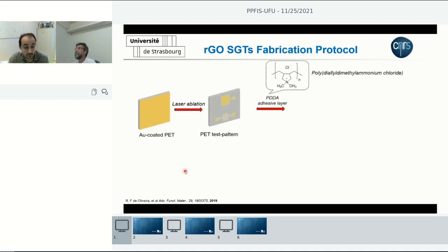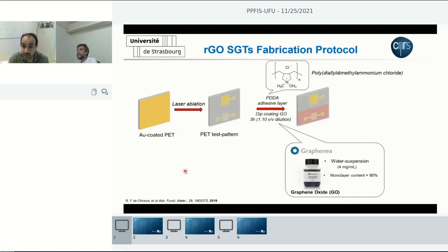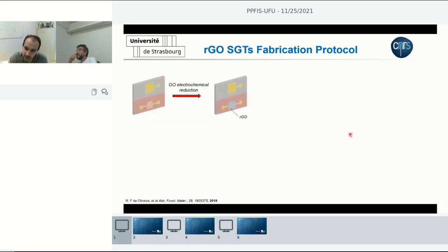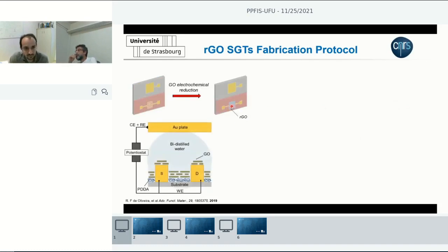We used an adhesive layer to keep the graphene oxide in place. So we use this polycation. We immersed our plastic substrate just to the middle, where we cover with this adhesive material, which creates a 1 nanometer thick adhesive layer. And then the graphene oxide, we use the commercial graphene oxide. So we cover just the pair of source and drain electrodes. And we reduce it just in the channel region to create reduced graphene oxide just here and not in the other parts of the device. This allows us to have spatial resolution.